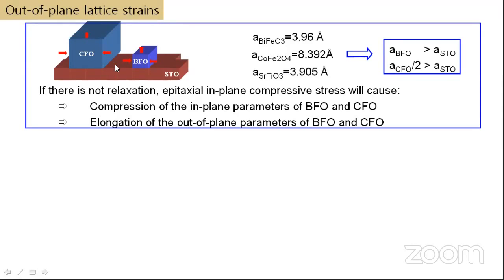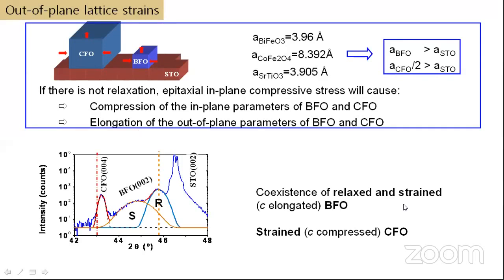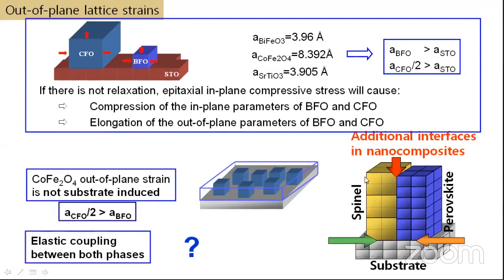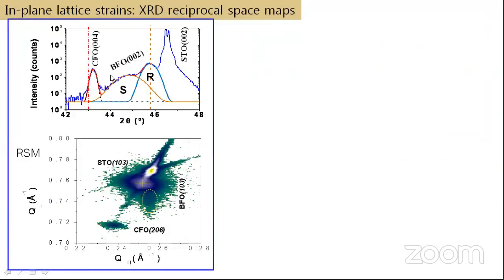So if we grow these alone, but what will happen if we grow them together? If you grow them together epitaxially, we have one additional interface here, between the spinel phase and the perovskite phase. This additional interface plays a major role in the elastic coupling. So we wanted to measure that strain at the interface between spinel and perovskite.